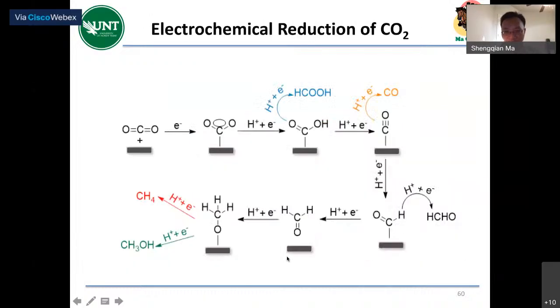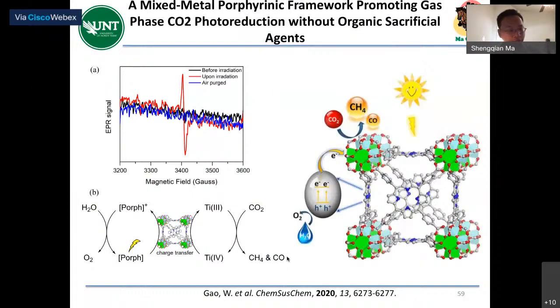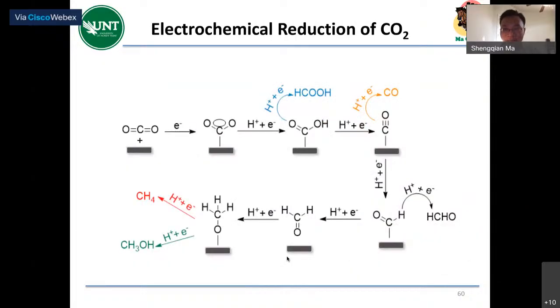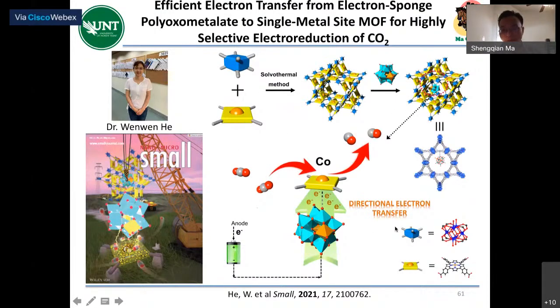In addition to mimicking photosynthesis, the artificial photosynthesis using this water oxidation coupled CO2 reduction, right? We can also use electrocatalysis, right, to supply electricity. Of course, this is much easier because we can use the electricity to directly inject the electron. So this is some of the process, using the CO2, the mechanism. Then we also pick the porphyrin. The cobalt porphyrin is well known to catalyze CO2. So the cobalt 2 can switch between cobalt 1 and cobalt 3. They can provide 2 electrons.